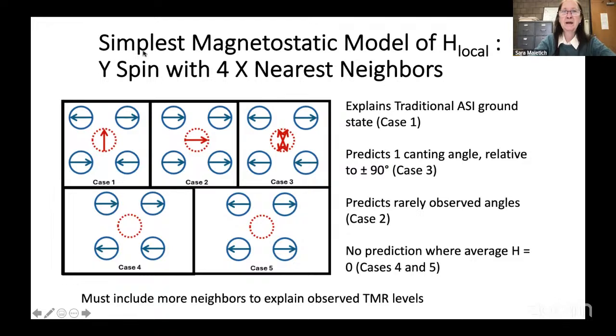So the simplest magnetostatic model of the local field would have your central spin and 4 nearest neighbors. And there are 5 different ways that you can arrange them. The traditional ASI ground state has the central spin perpendicular, plus or minus 90 degrees. This is what is seen with the elongated nanomagnets exclusively. If you go to case 2, you get a saturated state. We don't have a big field, so we don't see much of this. What we do see a lot of is this canting state. These are the different levels that we get if 3 of your neighbors point one way and 1 points the opposite direction. And then we get cases where the fields of the nearest neighbors exactly cancel. But of course, that just means that you need next nearest neighbors to break symmetry.